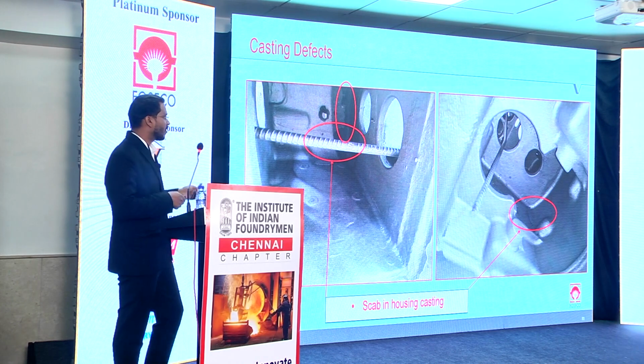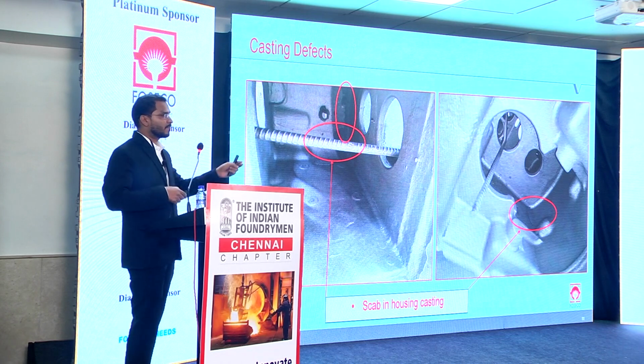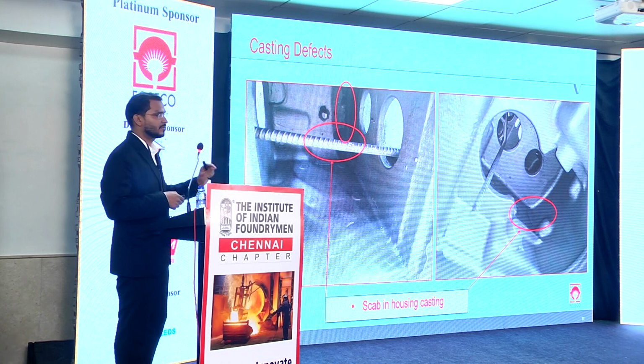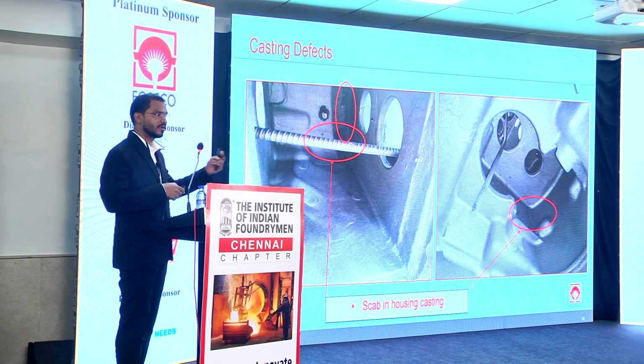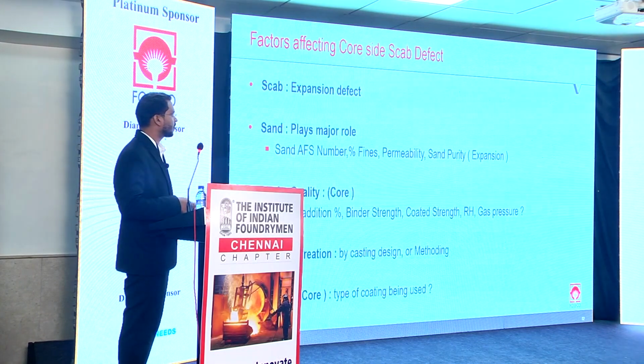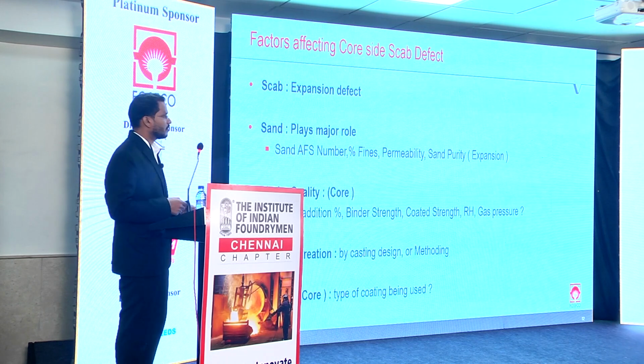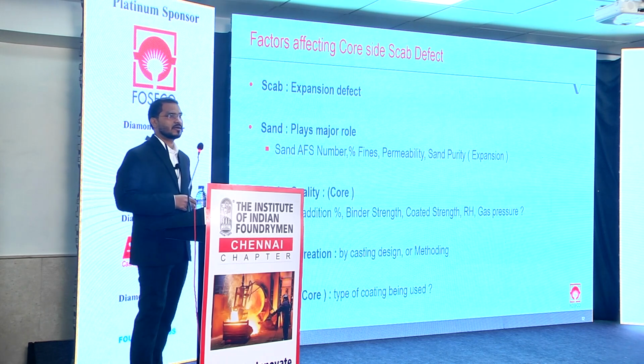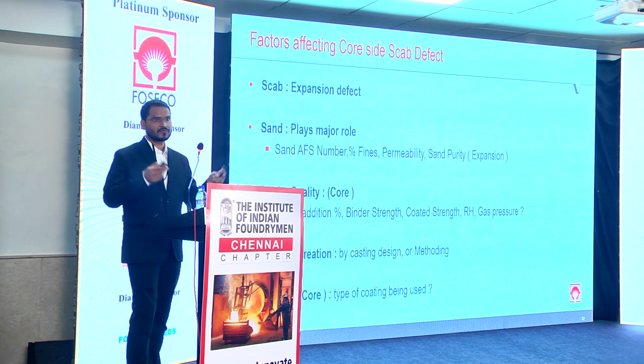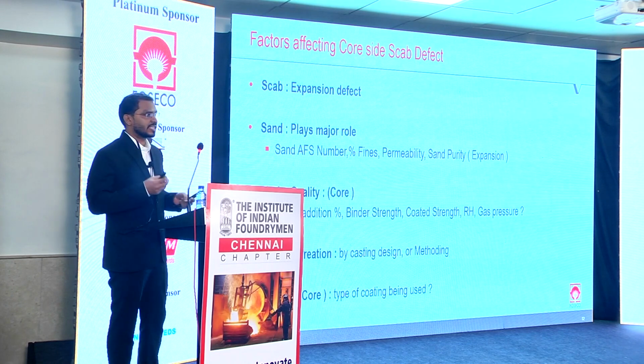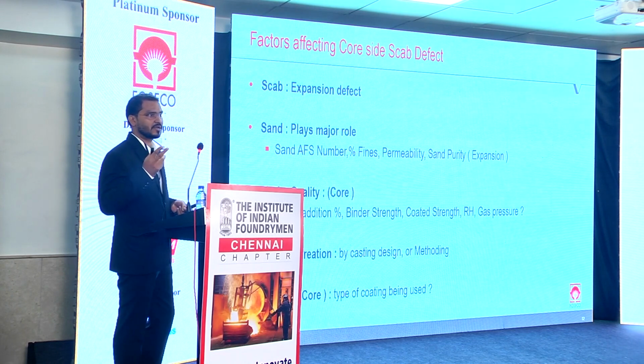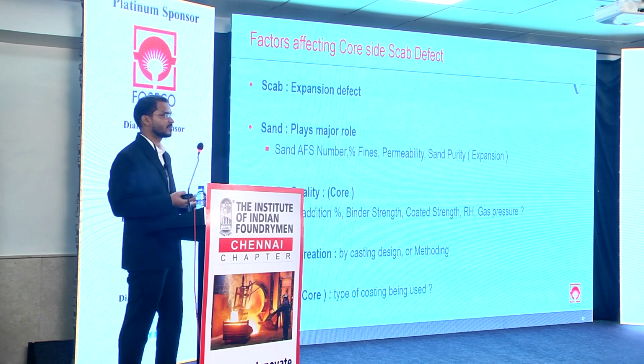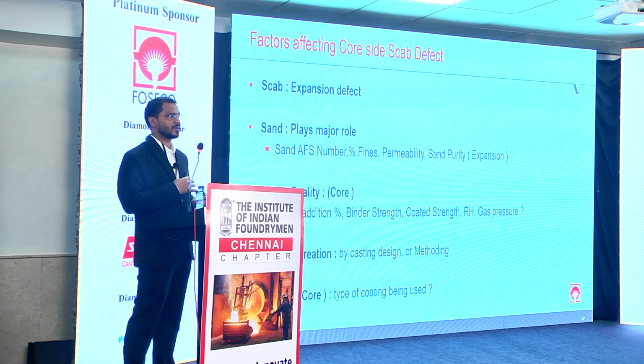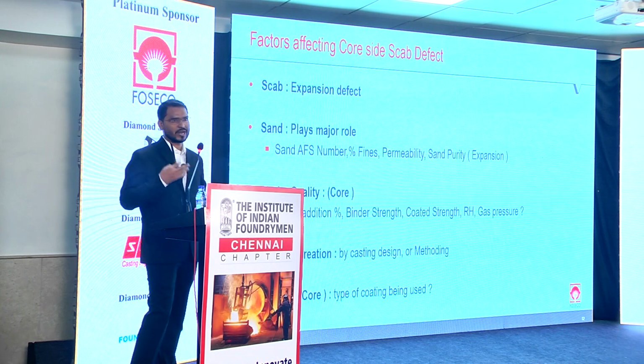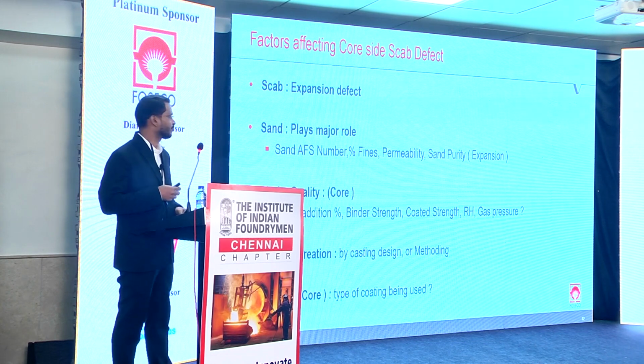So for foundries, it was difficult because it was not possible to remove this kind of scab by chipping. So they had to grind it, reprocess it, and then shot blast again. So the process steps were increasing. We all know why the sand scab defect is happening: because of sand expansion at elevated temperature. The scabs are of two types, one is expansion scab, another is erosion scab. Once expansion happens, the sand swells, and then because of metal static pressure and force, it is washed out. So two types of scabs happen.